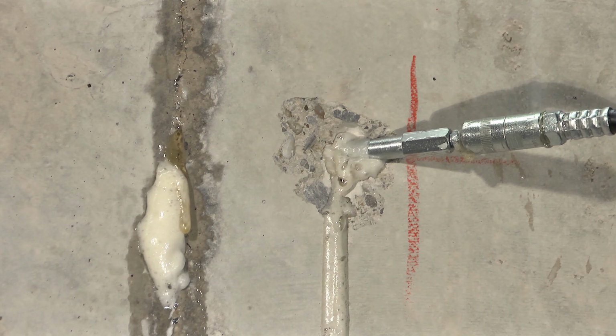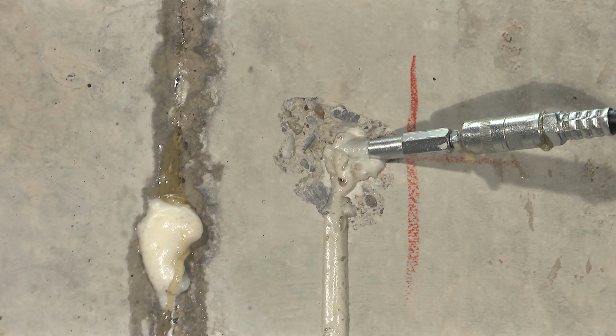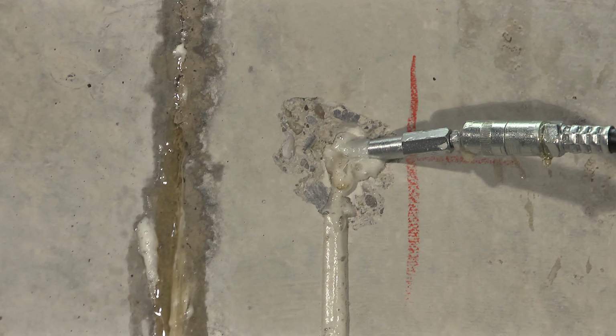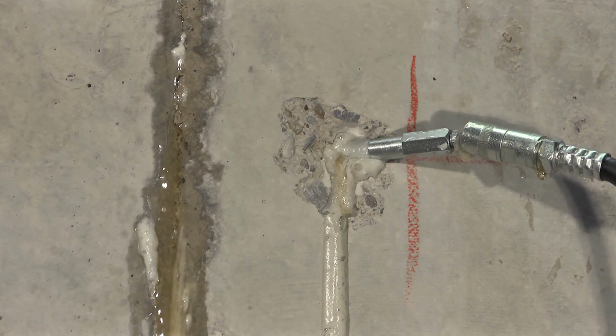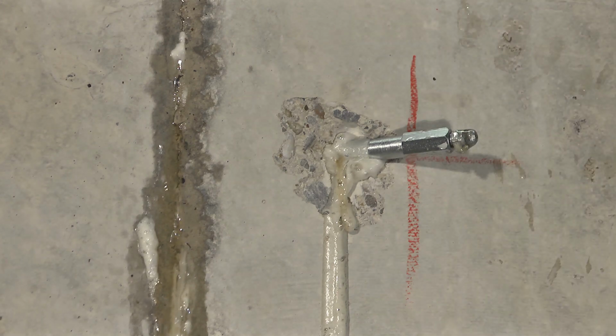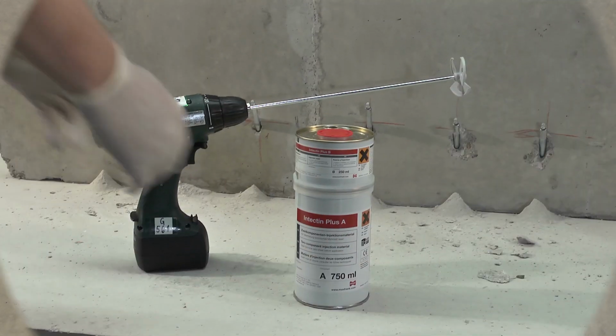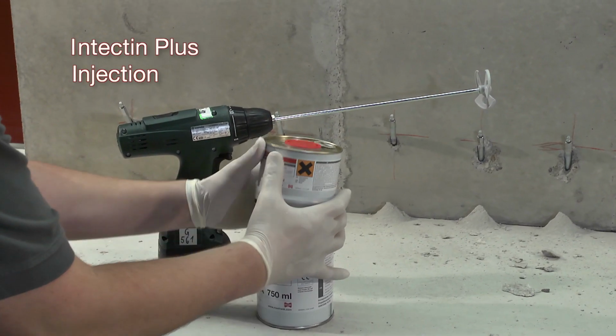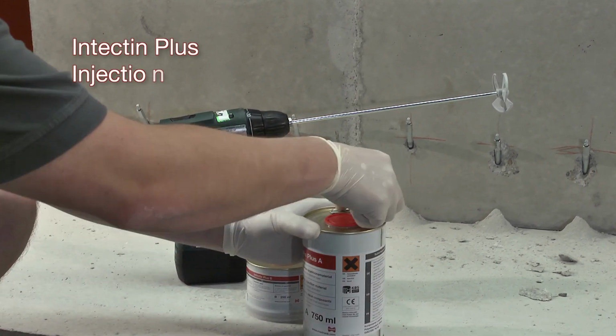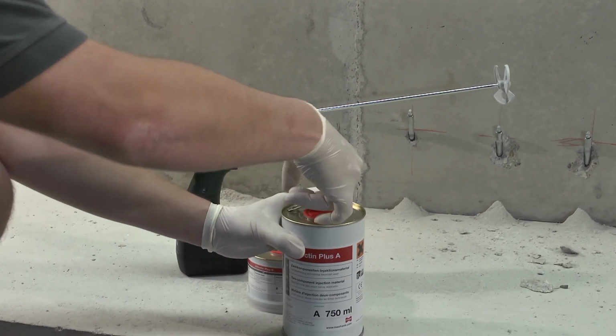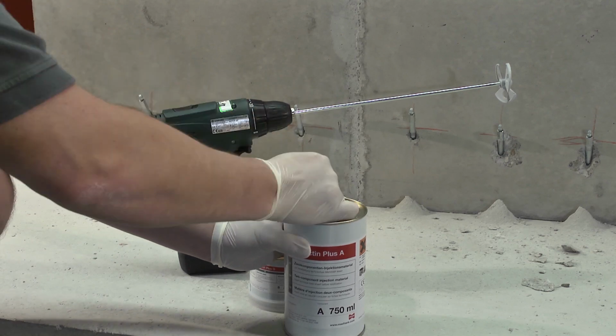Continue to inject the crack or joint with Injectin Blitz in the above sequence until the water flow within the crack or joint is stemmed. Afterwards, clean the injection equipment and tools prior to final grouting. When using Injectin Blitz, it is important to note that subsequent injection of Injectin Plus commences prior to curing of the Blitz resin. Otherwise, the packers cannot be filled with Injectin Plus, and new packers need to be placed.